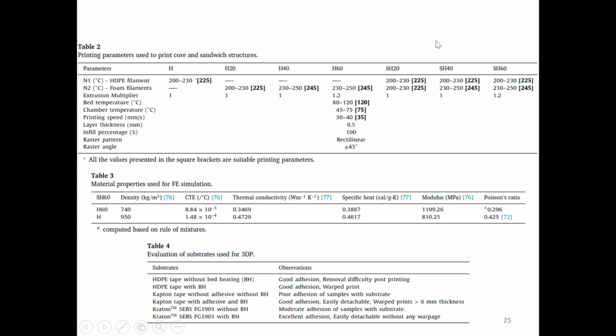So, as I was telling earlier, for printing core H20 to H60 and sandwiches, we exploited nozzle 1 and nozzle 2, available in any of the commercial fused filament fabrication based printers. I am using fused filament fabrication intentionally because fused deposition modeling is a copyrighted word, and thereby in our research group, while communicating journal papers, we never use FDM. We always use fused filament fabrication because this is synonymously used for FDM, and this is not a copyrighted word. So try to avoid using copyrighted words because many times reviewers get fumed, feeling that the authors don't even know which are copyrighted and why, and legal complications come in. So I always use fused filament fabrication.